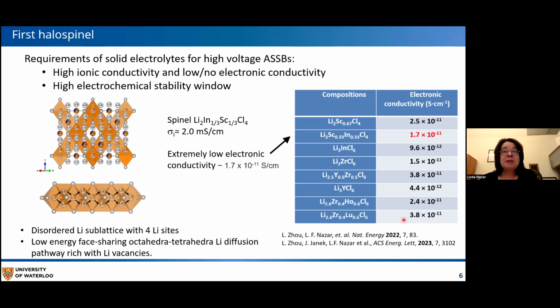And what this means is that it becomes more difficult to actually carry out the electrochemistry on the electrolyte because it is so insulating, sort of like LiPON. So it really renders it resistant to degradation. And this is just a sample of this picture of a cutout of this spinel lattice, and you can see the pathways for migration as the lithium moves from the octahedral to tetrahedral to octahedral sites. And this is somewhat of a limiting factor simply because the energy of these sites is different, so it causes a more convoluted landscape for that lithium migration. But it is a low energy face sharing arrangement, which is beneficial.